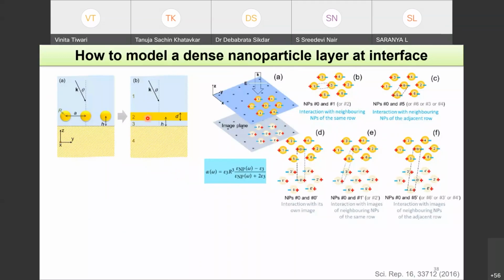So our main objective is to represent this nanoparticle layer as a layer of a fictitious material, but it should be a homogeneous and continuous layer, not a discrete structure. So we need to find out what is the effective polarizability of each nanoparticle in the presence of all other nanoparticles and the image that is formed in this interface.